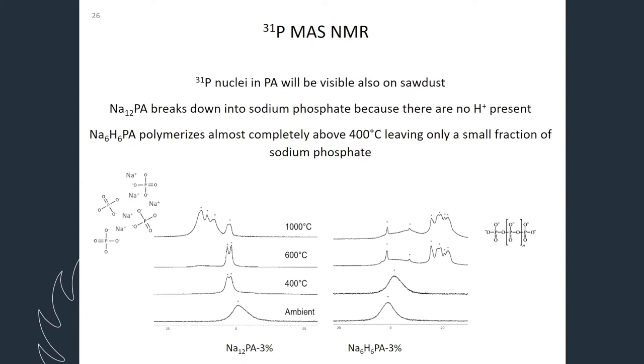When we look at carbon nucleus, then we can only look at the pure flame retardants because the cellulose has so much carbon atoms in it that we cannot separate the carbon from the cellulose and the carbon from our flame retardant. But there is no phosphorus in cellulose, so that's the perfect thing with looking at phosphorus, that we can see what is happening with the flame retardant when it is attached to some cellulose material, like sawdust.